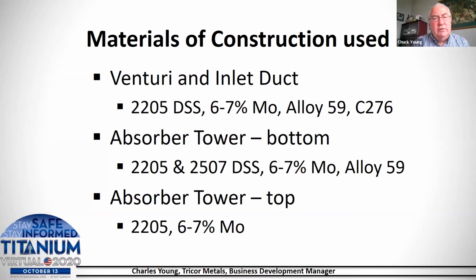But anyhow, the venturi and the inlet duct, and this may include where the wet-dry zone is, or the absorber bottom might be the wet-dry zone. But they're using a 2205 duplex stainless steel or a 2507 duplex stainless steel.